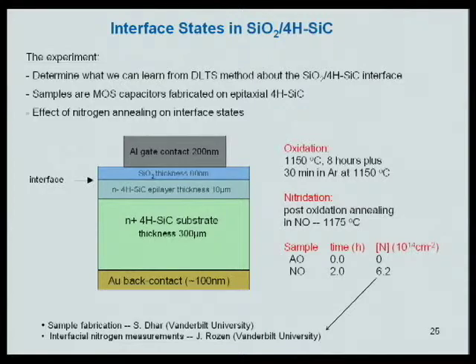What the Vanderbilt group finds is that after the nitrogen exposure, there's a measurable, detectable amount of nitrogen at this interface, within a couple of nanometers of the interface. They don't detect nitrogen in the oxide. They don't detect it in the silicon carbide, only at the interface. This seems to be proof that nitrogen is chemically reacting with something at the interface and changing the electronic properties. Okay, so we use capacitance measurements, capacitance spectroscopy.